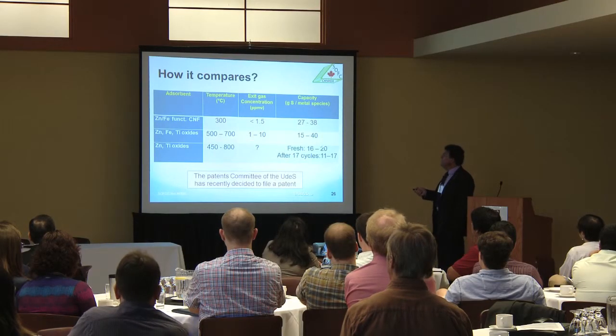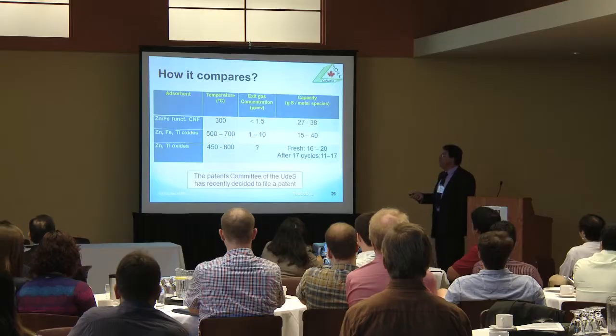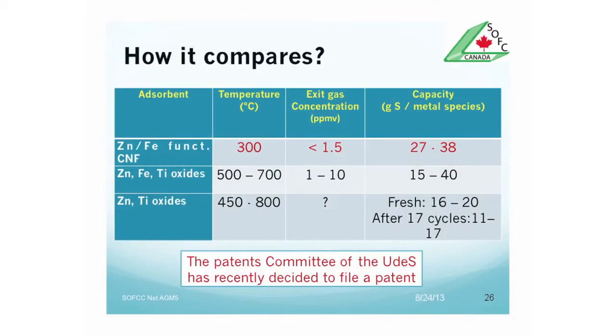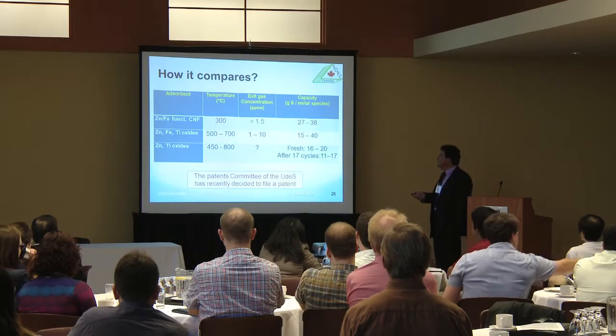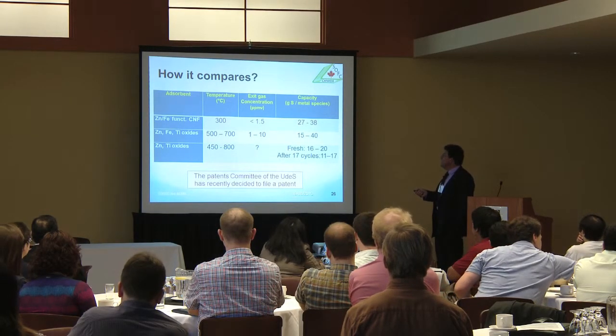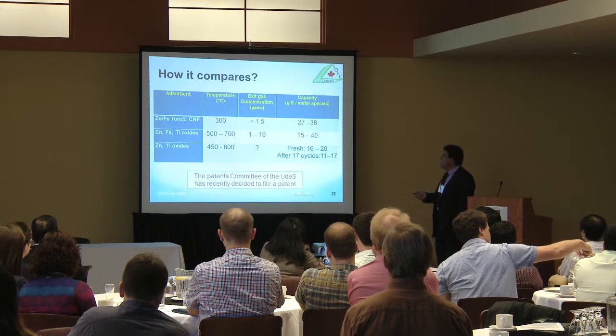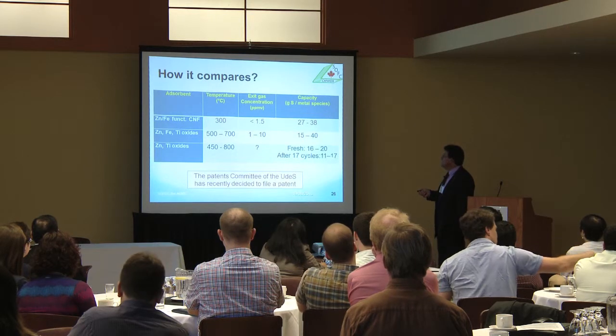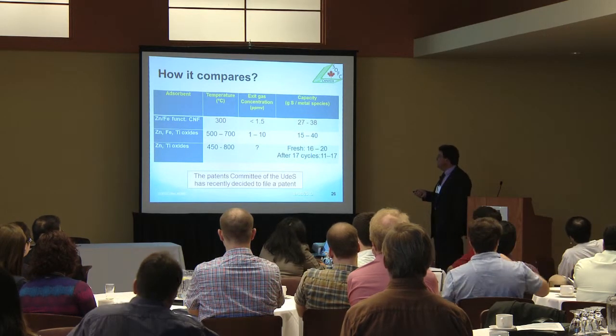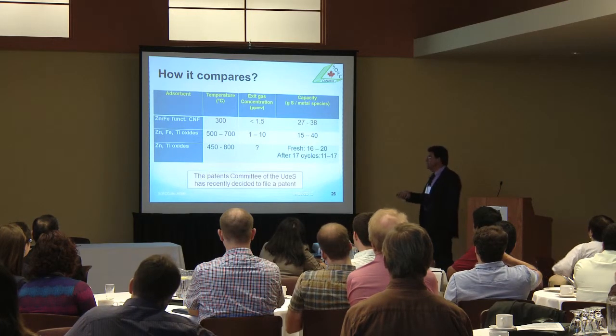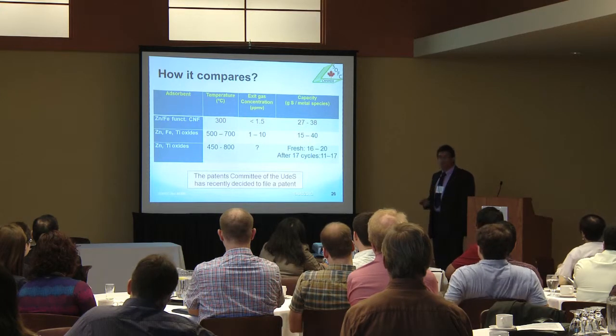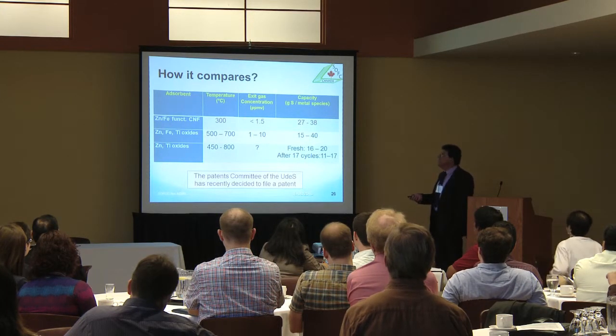And this is what happens in the literature with zinc, iron, and titanium oxides. We have to go between 500 and 700 degrees to get an exit concentration of 1 to 10 ppm, and the retention capacity is between 15 and 40. With other zinc and titanium oxides found in the literature, at these temperatures, they don't mention this. They mention, however, that the fresh catalysts have a retention capacity of typically lower than 20 and can be regenerated, and after 17 cycles lose about 10 to 20% of their capacity. So actually this has been presented to the Patents Committee of the University of Sherbrooke and has been accepted for filing a patent, which is ongoing.